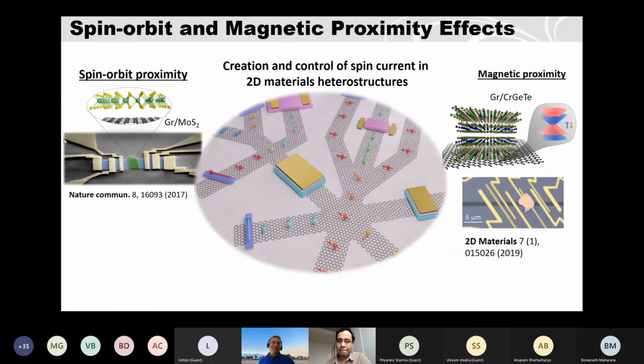So the first thing is about the interface, for example, this graphene MoS2. The interface should be very clean. So nowadays we are using a glove box to put them together, and we make sure the interface of the heterostructure is cleaner. And then the contacts are all made by electron beam evaporation. If you sputter or deposit, you have argon ions that can also cause damage.